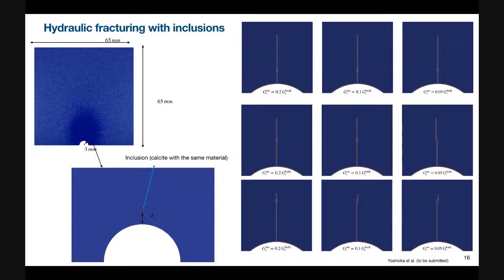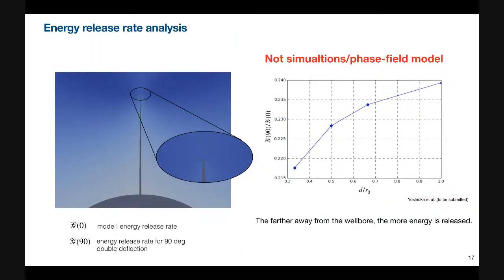But we want to know why this happens. This is not the simulation of the phase field models. I computed the energy release rate of a deflecting crack manually and normalized it by the penetrating case. So here's my calculation. This is the energy release rate of a deflecting crack, and this is the distance from the wellbore. This plot shows that the energy release rate of a deflecting crack increases with distance from the wellbore. This means that the crack tends to deflect more as it propagates farther away from the borehole, because the system wants to release as much energy as possible by fracture propagation. So from an energetic point of view, the crack may take a more complex path as it propagates farther away from the open borehole.